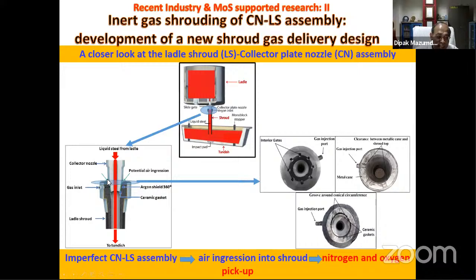What happens is, if you look at this joint, this joint may not be often perfect. And as a result of it, you inject gases here, and this gas tends to be distributed around the shroud collector nozzle joint. And this gas is an inert gas, which presumably will provide some kind of a shielding effect. And as you can see here, this is the gas injection port. So this design, if you look at the ladle shroud gas delivery designs, is an 8-port design here. So gas is injected here, gas comes out through these ports, and as a result there is a shrouding, or circumferential distribution of argon around the shroud collector plate nozzle.